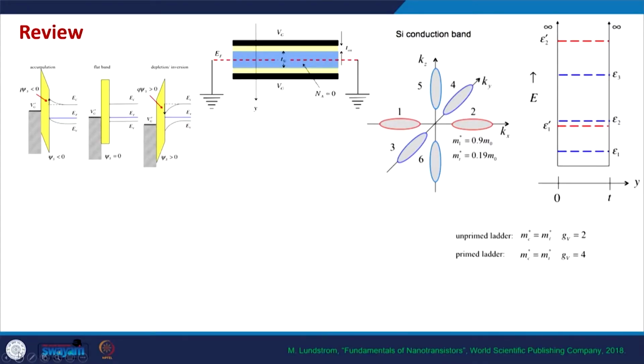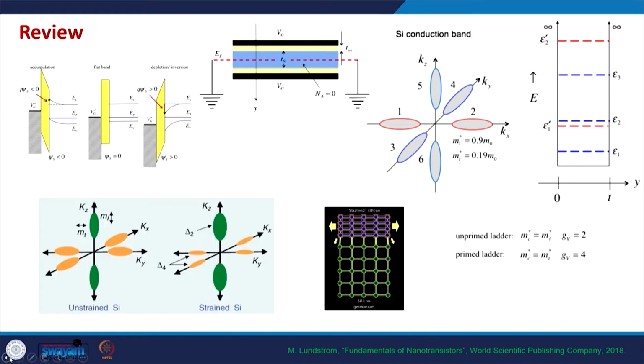So far we have seen quantum confinement in MOSFETs, and we also discussed strain engineering in silicon, especially in nanostructures in ETSOI MOSFETs. And what we saw was that if we grow the channel silicon on a silicon germanium substrate, we can change the band structure of silicon in such a way that, first, effective mass is modified such that the mobility is increased, and second, the inter-valley scattering in silicon is reduced. So by using strain in the proper direction, we can enhance the mobility or injection velocity of electrons in the silicon channels, and that's one of the very smart ways of improving transistor performance without changing the dimension of the transistor.